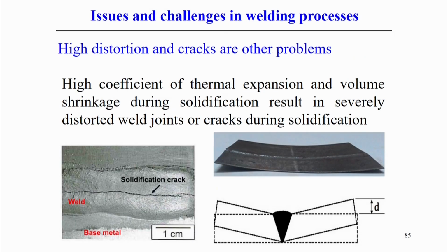In the final welded structure, even in fusion welding processes, high distortion and cracks are other problems. The distortion mainly comes from the coefficient of thermal expansion. It happens during solidification: after the application of heat, the molten metal becomes solidified, and solidification cracking may also occur. Solidification cracking is mainly due to a large change in volume, or basically very high volume shrinkage during solidification. That creates either solidification cracking or a large amount of distortion in the final weld structure.